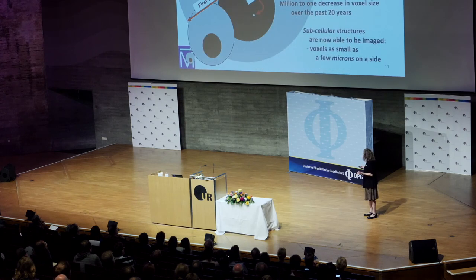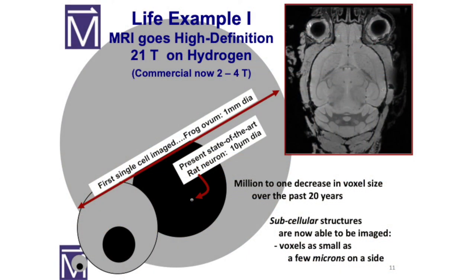Another example, and I have just two more examples, is why would you want to do MRI at very, very high field, 21 Tesla? When you go into an MRI machine, and probably most people here have done that, if you're over 25, what's the best part about going into an MRI? You get to go inside of a superconducting magnet, okay? So that's pretty cool. But this is actually not the 2 to 4 Tesla that you get in commercial MRIs. This is 21 Tesla. So if you're looking at something dead, like a cell imaged, you could see 1 millimeter diameter if you're at low Tesla, but if you're going to 21 Tesla, you can actually go down to microns diameter of seeing things. So you significantly increase the resolution.